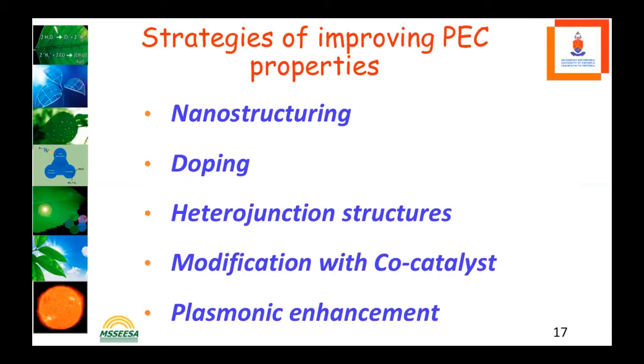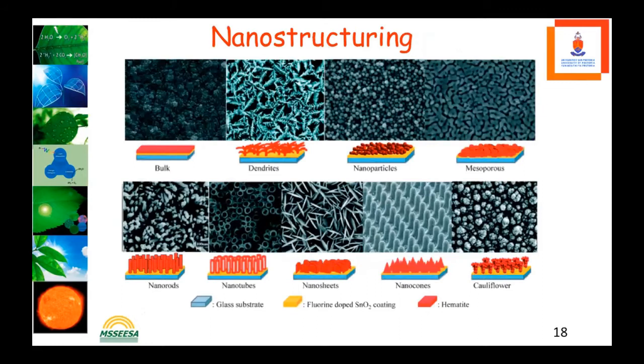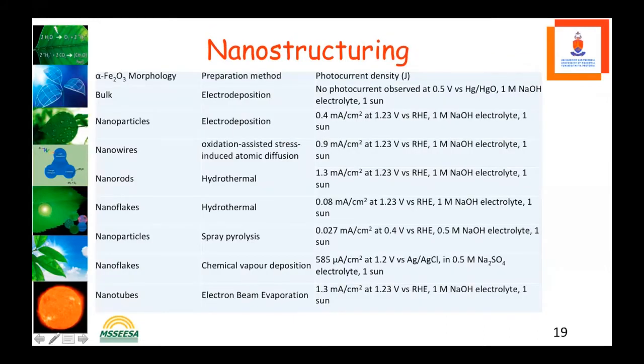And we can use a co-catalyst and the plasmonic enhancement of using metal nanoparticles. These are the different achievements by many other people of making nanostructures of hematite. You can see nanorods, dendrites, nanotubes, nanosheets, nanocones, cauliflowers, and generally it has to be mesoporous. So nanostructuring, in the results that we have found, has given